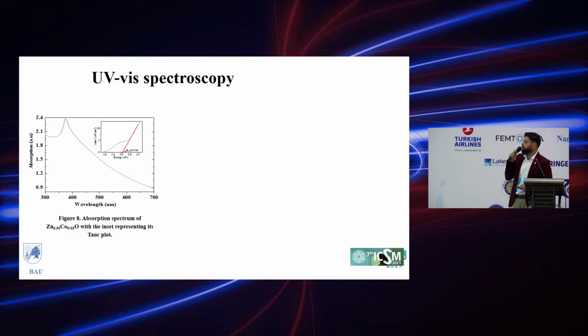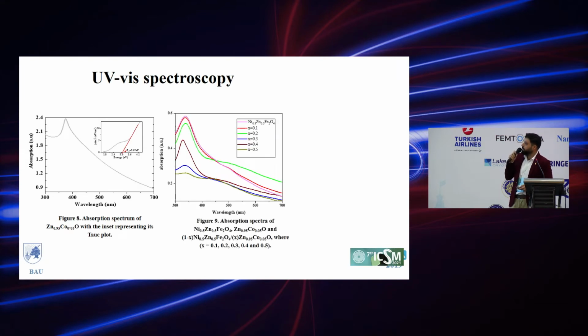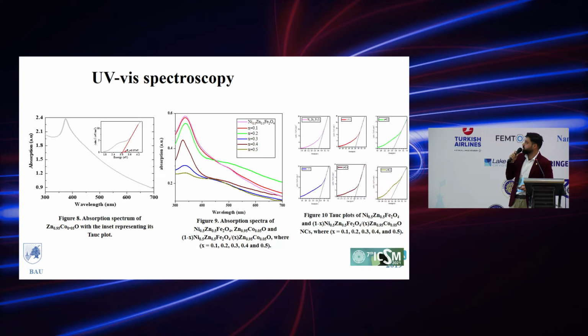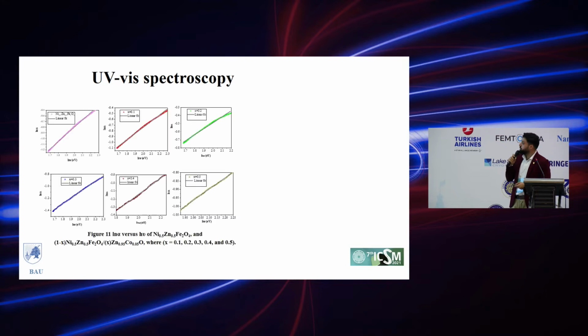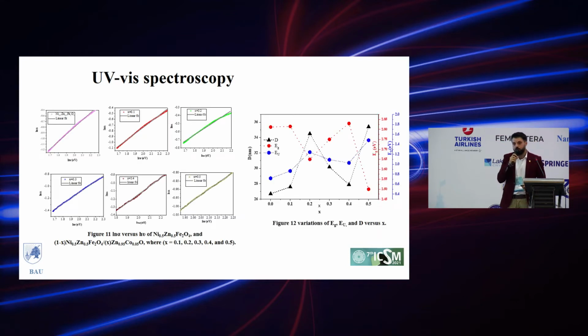The optical properties, starting with the ultraviolet visible spectroscopy, the absorption curves for all samples were shown, and the famous Tauc plots were employed in order to determine the band gap energy of all samples. Now, in nanocomposites, introducing two nanophases together causes a distortion in the band structure of the nanocomposites. So this is why it's interesting to study this distortion by doing the Urbach analysis.